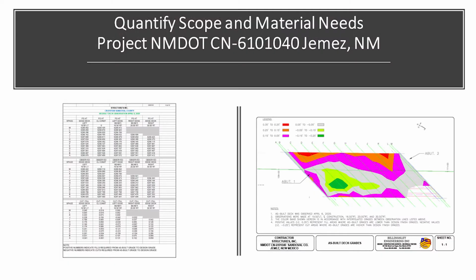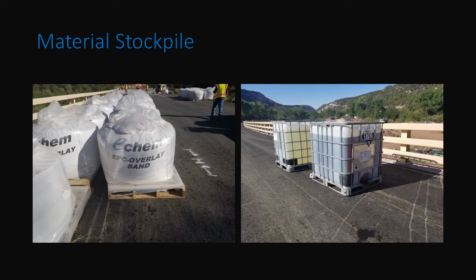There were multiple concerns about this project and the viability of rescuing this deck. So we were able to come in, help the DOT come up with a process, and came together with a contractor to get this done. It was about a 60-day delay by the time we started, evaluated it, and got it to the point where we were able to correct it. So we figured out how much material we needed. We got all the material on site.